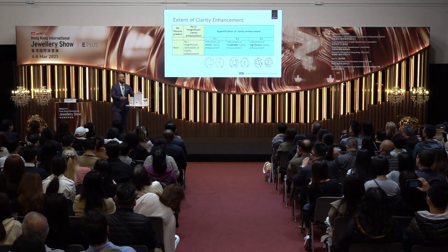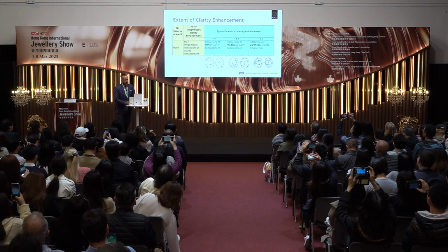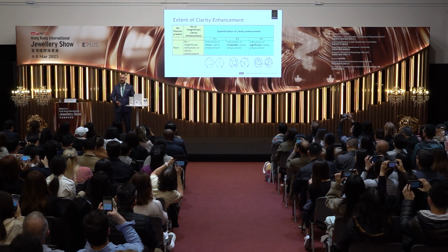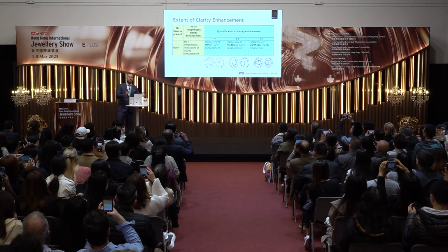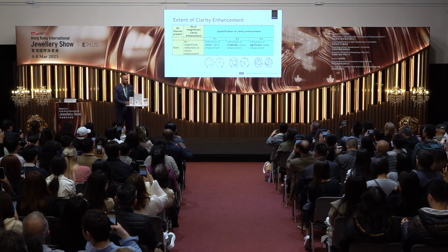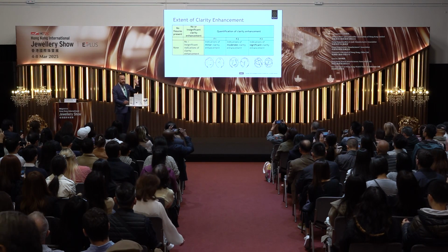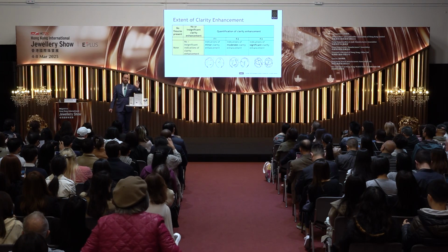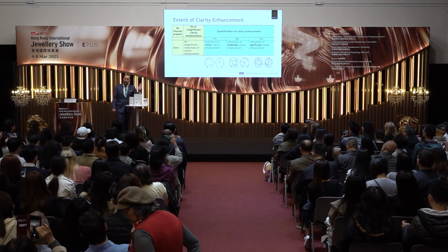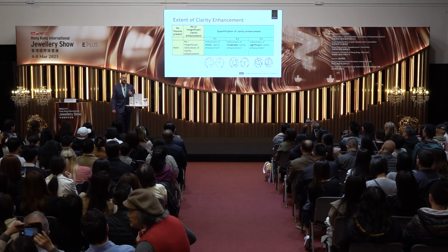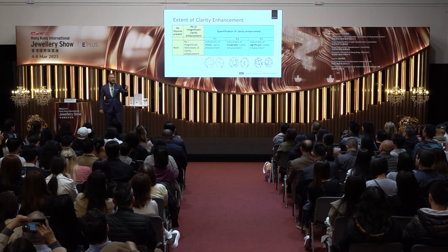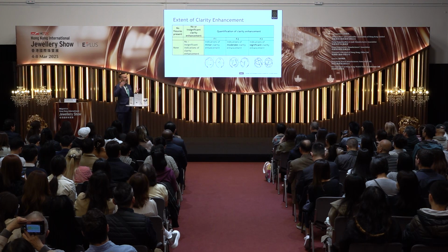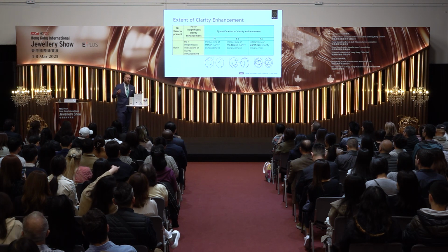And then we have the stones where we detect clarity enhancement. So that is a terminology that is adopted among most of the laboratories and is very consistent there. Our good friends from GIT, from SSEF, from Gübelin use the same kind of categorization, where we separate between minor, moderate, and significant, F1, F2, F3, based on the presence of the fracture, the location of those fractures, but also based on how deep are those fractures, how wide are they.